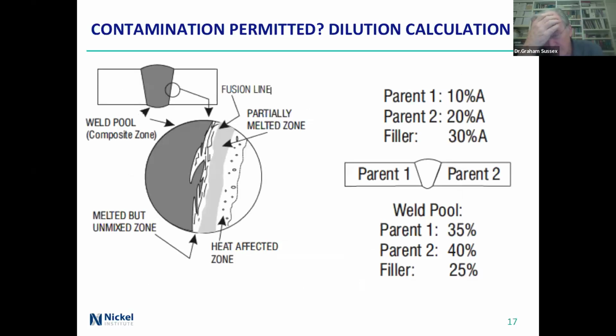So what happens when you actually weld something? You've got the weld pool, you've got a melted but unmixed zone. You've got the fusion line just on the side of that, the partially melted zone, and the heat affected zone, which is out on the outside. Then you do a dilution sum and work out what's going to happen in the weld pool compared with the sums that are in there, parent 1, parent 2.